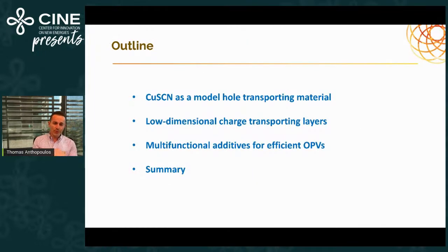I just tried to go through some of the important work that my group did over the past 5 years or so, starting with the use of copper thiocyanate. This is an inorganic wide band gap semiconductor that can be solution processed and is p-type, hole transporting in character. Then I moved to some interlayer technologies, which are related to low dimensional materials. And I will finish with some multifunctional additives, essentially dopants that we have been introducing into the bulk heterojunction of our devices to improve the overall performance of our OPVs, as well as their operating stability.